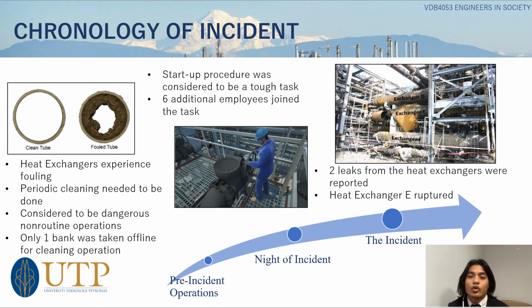6 additional Tesoro employees, consisting of 5 operators and 1 supervisor, joined the outside operator at 10:30 p.m. for the startup of the heat exchanger. The roles of these 6 additional personnel had not been specified in the startup procedure. During the startup, 2 leaks from the heat exchanger were reported, and the leaks did not stop the operation as they were considered frequent and had become a normal part of the startup. At 12:30 am on 2nd April 2010, the E heat exchanger on the adjacent in-service bank catastrophically ruptured, while the 7 operators were still performing the startup operation for the ABC heat exchanger bank.